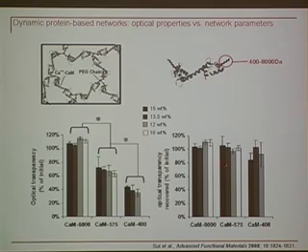And importantly, these materials recover. So in each case, we get no significant shift, we get no significant hysteresis, essentially. We don't get changes in optical properties that persist over an extended time frame. This is somewhat important because it suggests that the shift in optics doesn't have to do with protein crashing out of solution and forming what would amount to an inclusion body, but instead has to do with some sort of heterogeneity in the cross-links that leads to optical shifts.